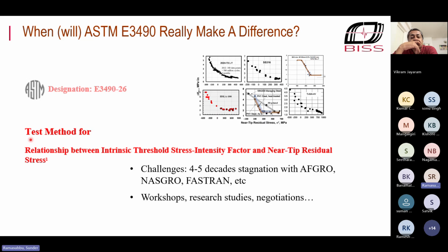And you raise a very important point, because these factors, they affect the near threshold behavior much more than they affect the behavior at higher growth rates. Yeah. In the Paris regime, even between air and vacuum, the difference will not be phenomenal. Right. But when you go further down, it's a huge difference. So, yeah. Thank you. Yeah.